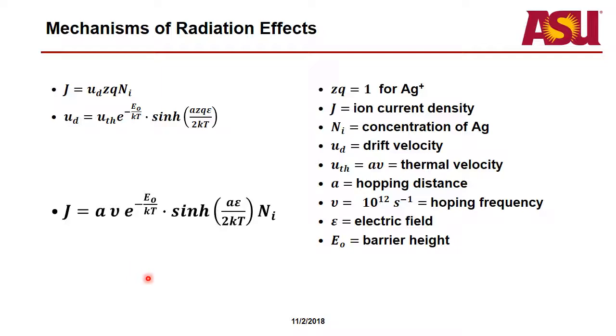So essentially, if say we're comparing how this ion current supply is changing with material changes from, say, going from alpha to beta, for the most part, this barrier height will increase, but not significantly. So maybe I think the initial barrier height for the alpha phase is very close to zero, actually, but can vary to about 0.2 eV.